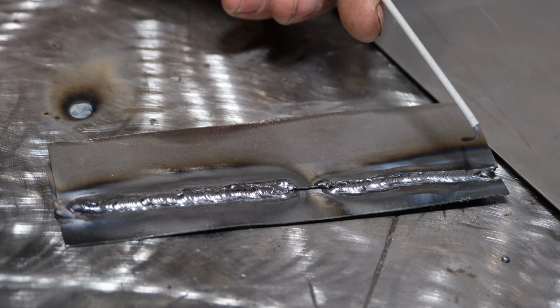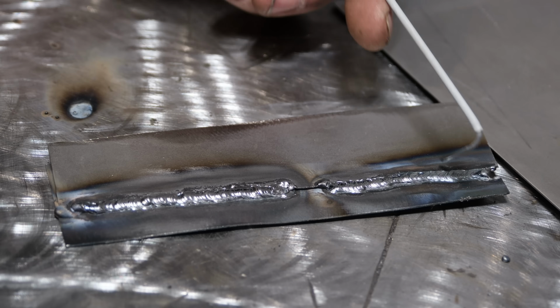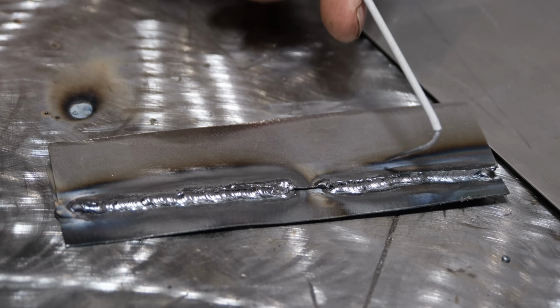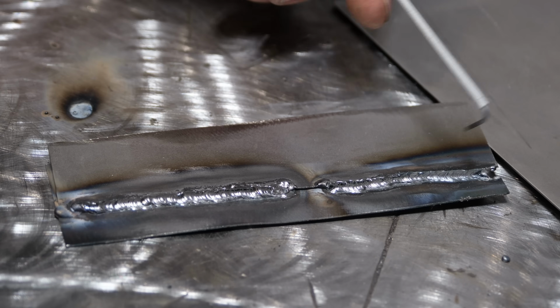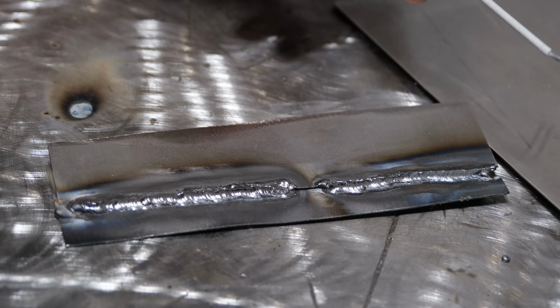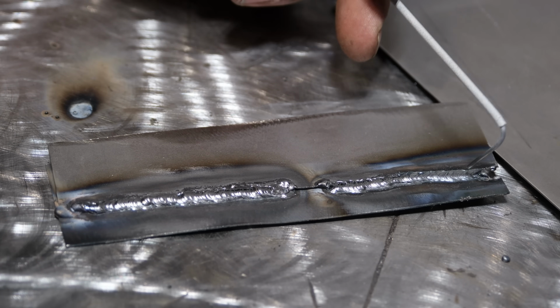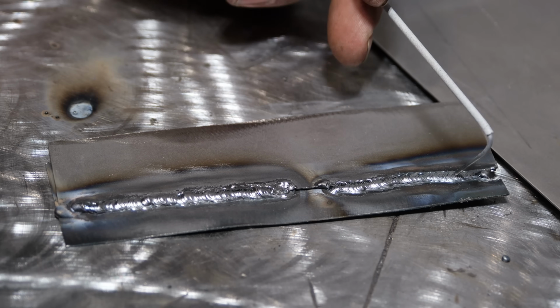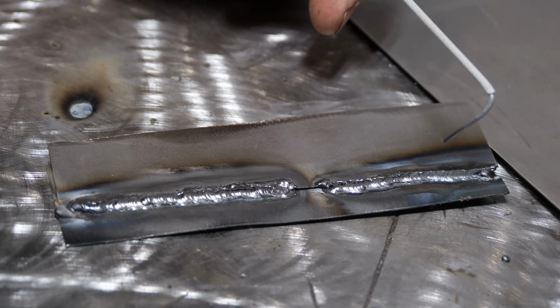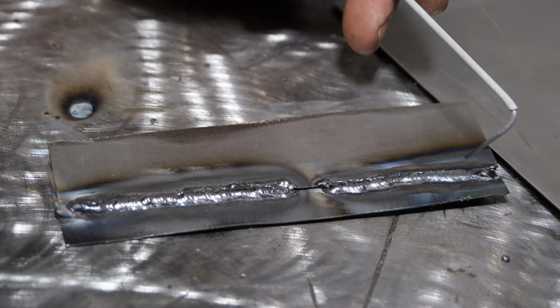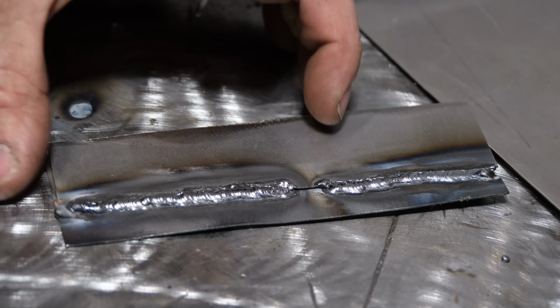I'm sure with more practice, I could probably make it look pretty good the whole length, but that arc wandering issue is still going to be an issue. Again, dialing in amperage, I was at about 26 amps, and that seemed to be okay. Anything more than 30 amps, and it's just going to blow holes through it.